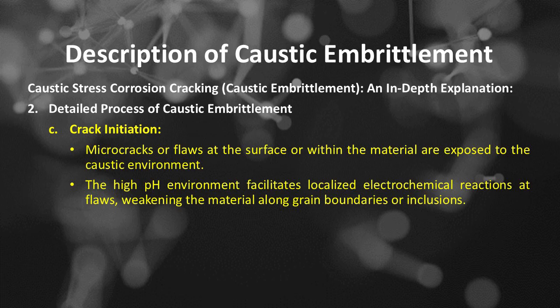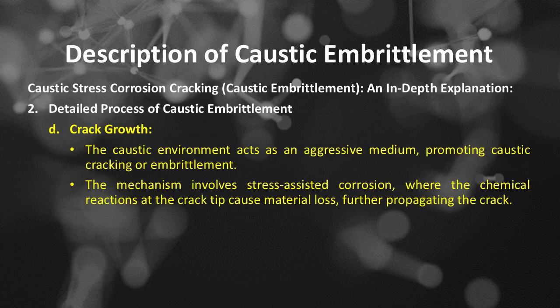Process of caustic embrittlement. Number C, crack initiation. Microcracks or flaws at the surface or within the material are exposed to the caustic environment. The high pH environment facilitates localized electrochemical reactions at flaws, weakening the material along grain boundaries or inclusions. Process of caustic embrittlement. Number D, crack growth. The caustic environment acts as an aggressive medium, promoting caustic cracking or embrittlement. The mechanism involves stress-assisted corrosion, where the chemical reactions at the crack tip cause material loss, further propagating the crack.